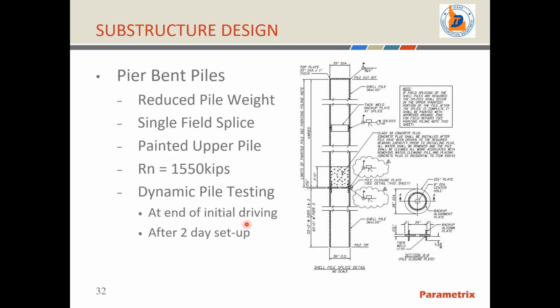That would complete the end of initial driving. The contractor was actually required to do dynamic pile testing and confirm with CAPWAP analysis. And if the driving did not achieve the required nominal capacity at the end of initial driving, the contractor was required to wait 2 days for pile setup and then retest the pile. All the piles came to capacity after having to do a two-day setup. They did have to do the 2-day setup, but it was good that we got the capacity that we needed because 1,550 kips is not a small capacity to confirm.